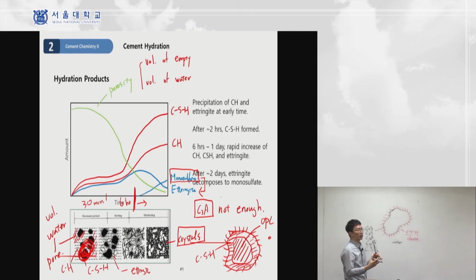The reason why the concrete has some strength is because calcium silicate hydrate is the main contributor to the strength of this composite material. So there's a reduction of the cement particle, because this part has reacted with water to form CSH, right? So still it has a cement part here. This is unreacted cement. Unreacted, still intact, unreacted part. But for further hydration or subsequent hydration, the water should go into the CSH to be hydrated more, right?